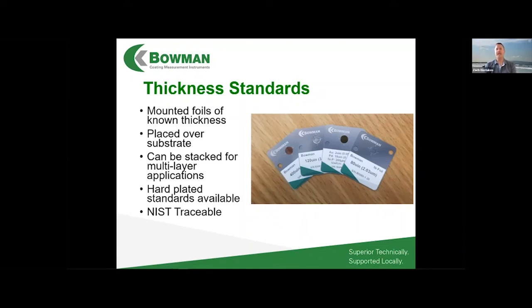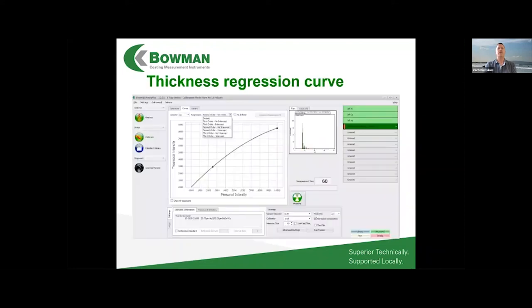They can be single or multi-layered foils that are mounted onto these thin little sandwiched mounting plates. Then you lay those over the substrate, you put them into the machine, and you measure them. Again, that represents your actual plating process, and they are NIST traceable. Once you lay those in and measure them, you get a regression curve. Again, you've typically got a second order type of relationship between thickness and intensity.